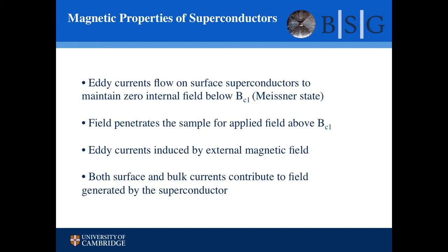Okay, so just to summarize the magnetic properties of superconductors, in some ways they're easier to understand than normal conductors because there's no resistance, but eddy currents flow on the surface of the superconductor to maintain this zero internal field below some critical field. Above that field, BC1, field starts to penetrate the superconductor. Eddy currents are induced by the applied magnetic field, so a changing field gives us these currents. And both surface currents and currents within the bulk of the material contribute to the magnetic properties of the superconductor.